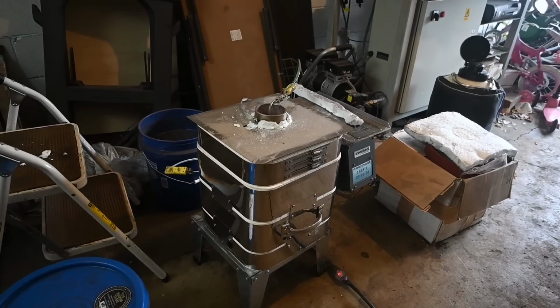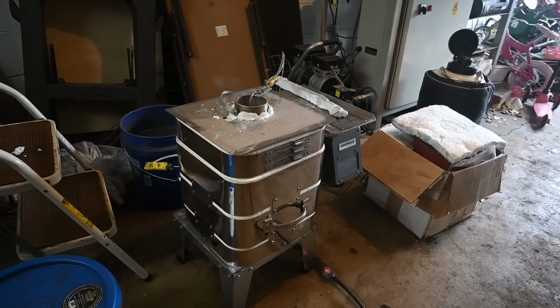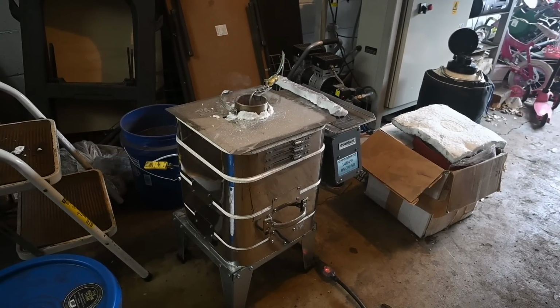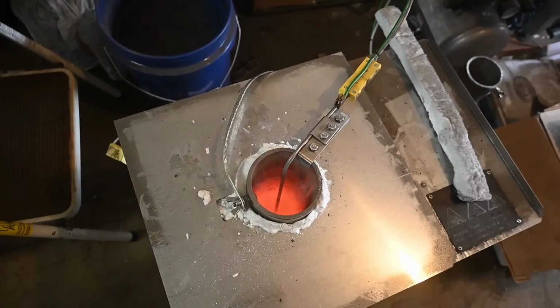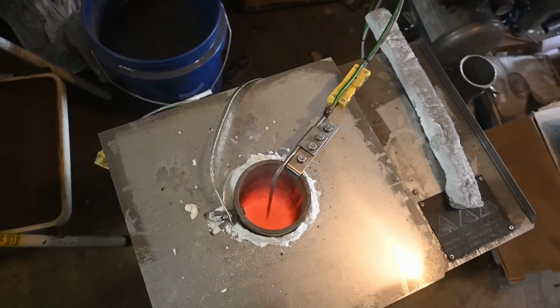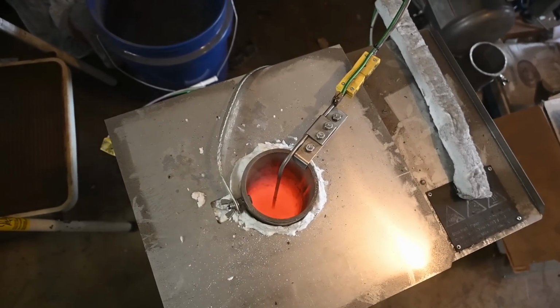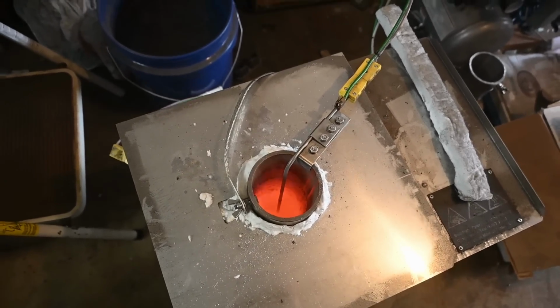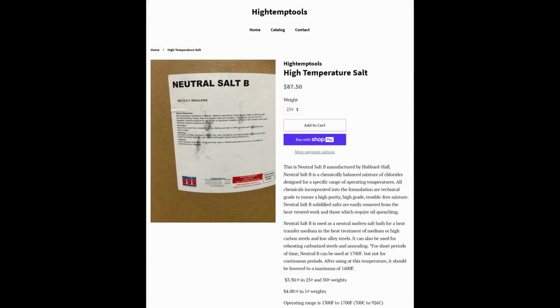This is a heat treating technique that uses molten salts. So you use a special kind of salt, it melts, and then you've got this hot liquid that you can stick the steel into. For these experiments, I used Neutral Salt B by Hubbard Hall. I got it from High Temp Tools. They sell salt in relatively small amounts, so it's easy to buy.